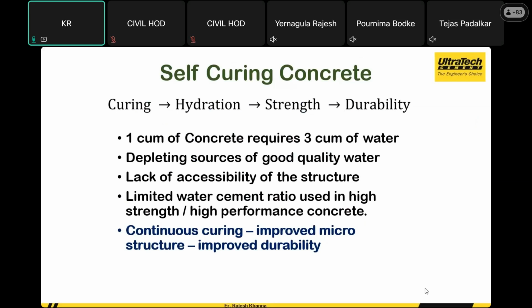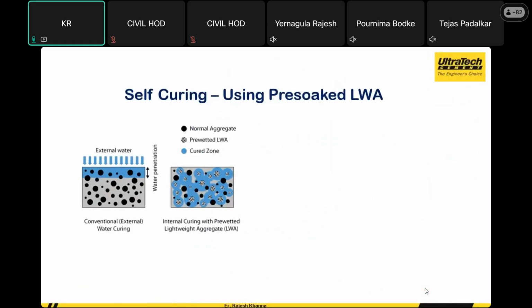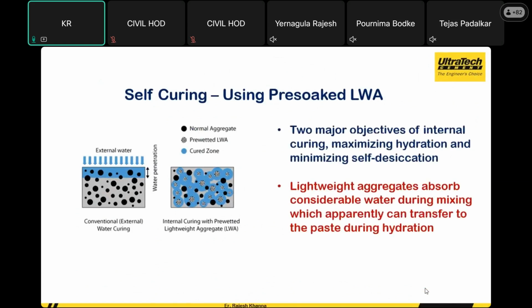So with the depleting sources of good quality water, we are lacking accessibility for the structure, because a limited water cement ratio is used for high strength and high performance concrete. Continuous curing has to be given. But now, when we have a shortage of water, where is the option to go ahead with this? So we have this system called self-curing, using pre-soaked lightweight aggregates, or even after completing the concrete and deshuttering it, we apply this curing compound onto the surface soon after deshuttering, so that there won't be